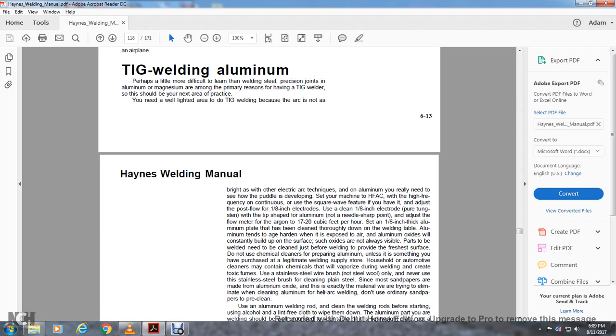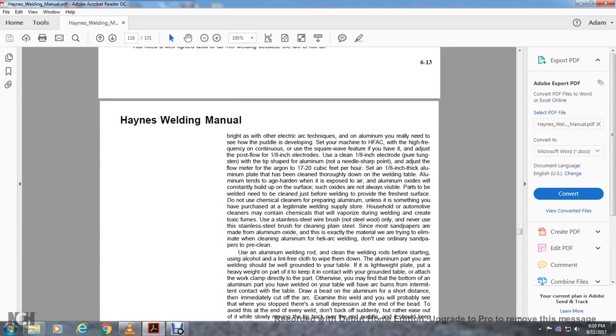Do not use chemical cleaners for preparing aluminum unless it is something you have purchased at a legitimate welding supply store. Household automotive cleaners may contain chemicals that will vaporize during the welding and create toxic fumes. Use a stainless steel wire brush, but not steel wool. Never use the stainless steel brush for cleaning plain steel. Since most sandpapers are made with aluminum oxide, this is exactly the material we are trying to eliminate when cleaning the aluminum for heliarc welding. Do not use ordinary sandpaper to pre-clean.